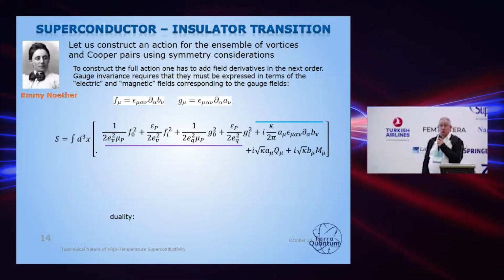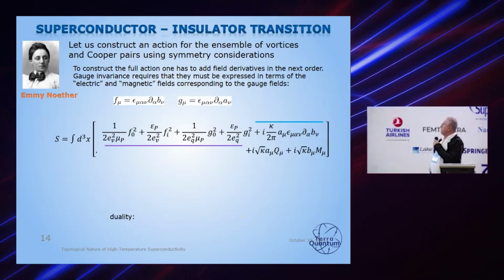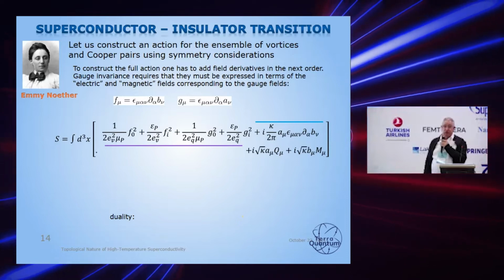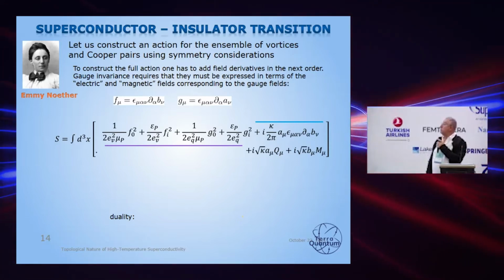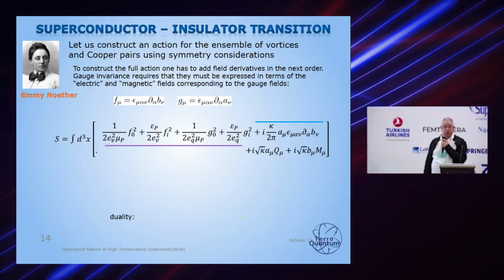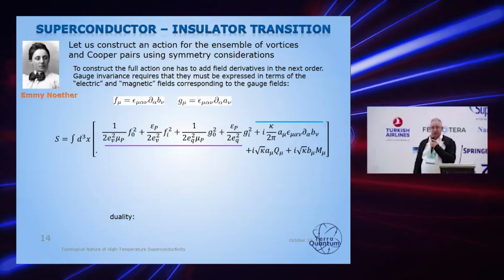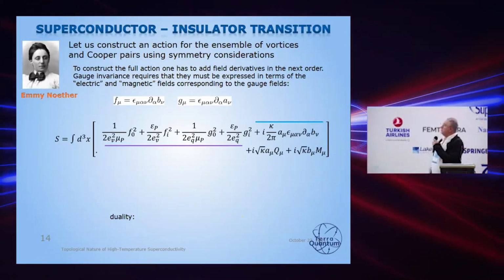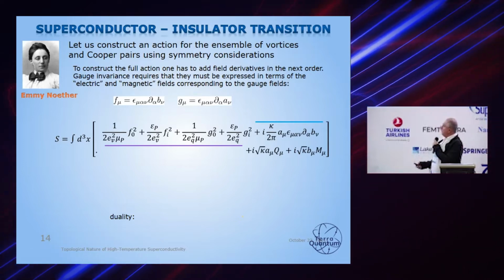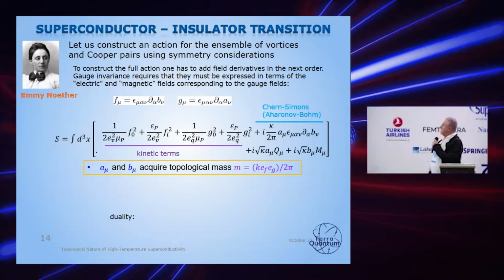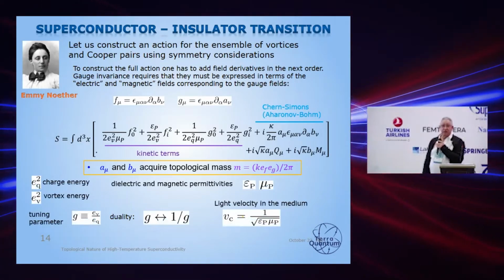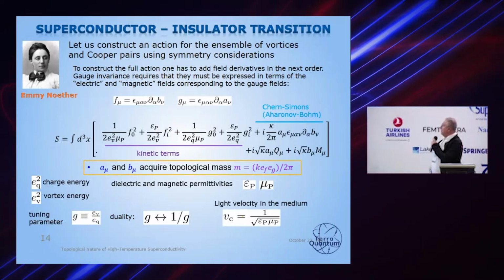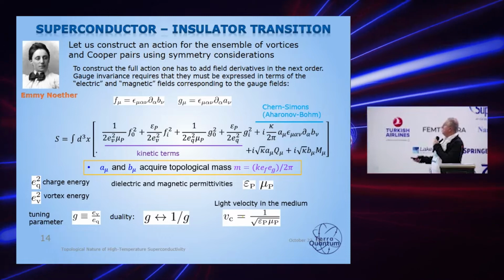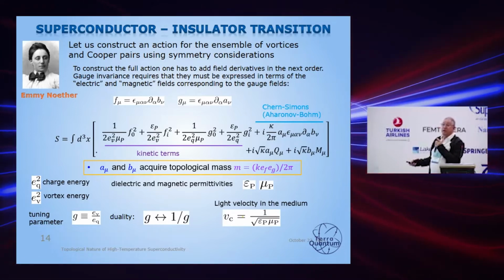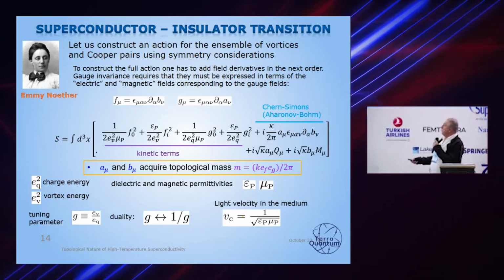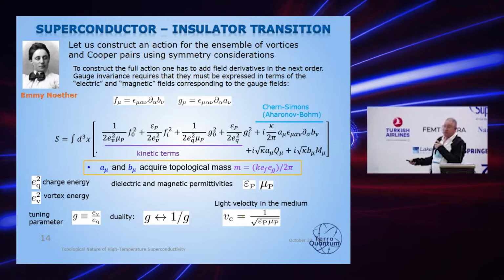Well, to go a little bit further and construct the full theory of the superconductor insulator transition at finite temperature, one can just go along the route outlined by Emmy Noether, another of the greatest minds of the 20th century. Just using symmetry considerations, we can immediately write down the action, exactly the same way it's done in all the textbooks, and immediately see that we can indeed recover all the magnetic electric duality. So this action doesn't contain anything miraculous or unusual. We have the usual kinetic terms as in any textbook.